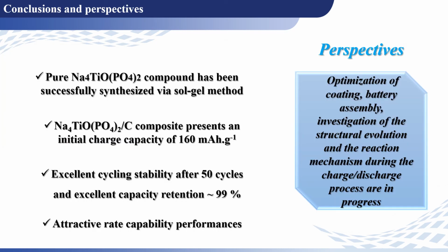To conclude this presentation, I will make the highlights on the main axes treated. A pure sodium titanium phosphate has been successfully synthesized via the sol-gel route. The carbon-coated sodium titanium phosphate presents an initial charge capacity of 160 mAh per gram with excellent cycling stability after 50 cycles and excellent capacity retention approaching 99%. As perspective, we are looking forward to performing in operando XRD analysis to investigate the structural evolution and the reaction mechanism during the charge-discharge process.